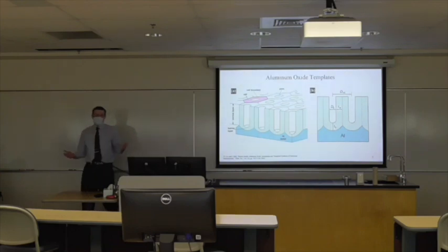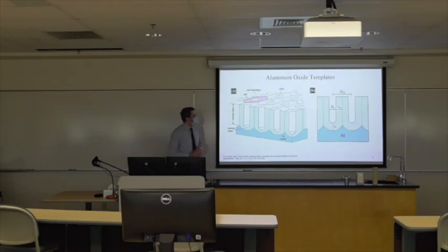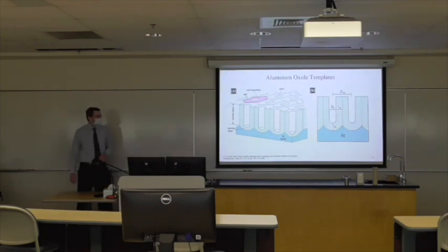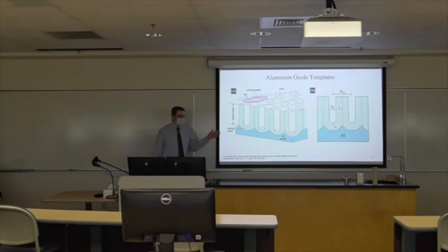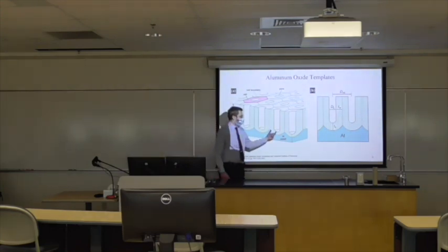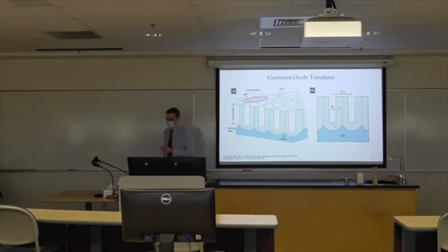So we need to have templates in general to make those sorts of things. Now, the most commonly used templates are aluminum oxide templates. This exploits a property of aluminum where, put under electric potential in the presence of certain electrolytes, the oxide layer will thicken and will have pores formed in the layer. These pores exhibit hexagonal cells in the aluminum oxide and expand vertically, essentially as far as you would like them to go.